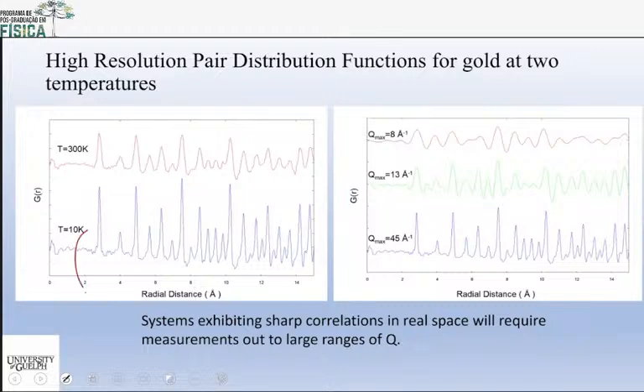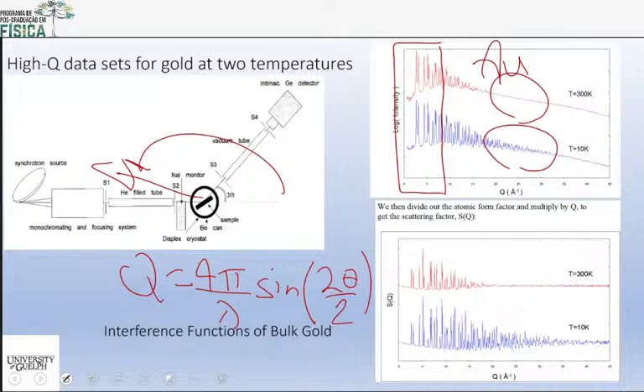But now what do the peaks correspond to? There's the nearest neighbor. That's at 2.4 angstroms or whatever, telling you that that's where you're going to have a gold atom. So every gold atom will have no atoms really, really close to it, and all of a sudden it'll have a bunch. And if it's face-centered cubic, by the way, the area is going to be 12, okay? That's the number of nearest neighbors, so the area of the curve corresponds to the number of neighbors, and the position is the distance, okay? And there's the next nearest shell, and so on. So that's how you get information about, okay, even a nanoparticle, okay? We did not need to measure the sharpness of the Bragg peaks. We just had to measure further out in Q space.